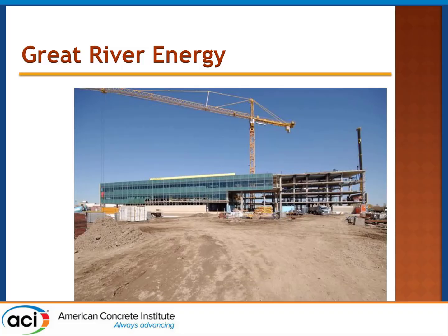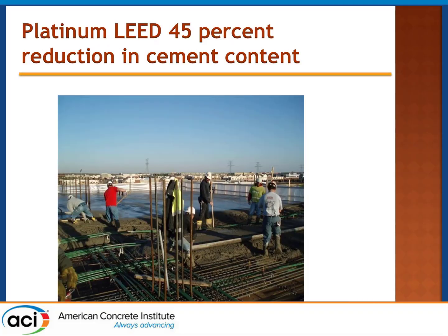And they said, I want this building to have as much fly ash in it as possible. And the architect called me up and said, hey, how much can we put in? Thinking, I want to go from 25 to 35. And I said, well, 65 without doing too much work, and we could probably do better than that. So we had a target for platinum LEED. It was a 45% reduction in our cement content, our ground clinker and various other things content, and we met that requirement, and the owner was very happy.